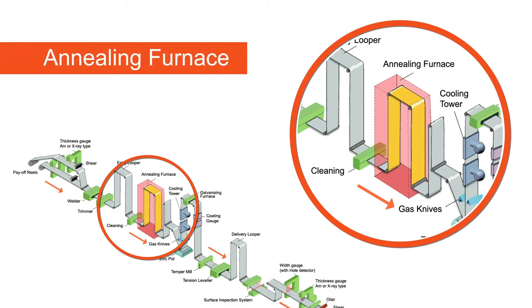An annealing furnace that is used to heat the steel to high temperatures to impart the desired mechanical properties such as strength and formability to the steel sheet.